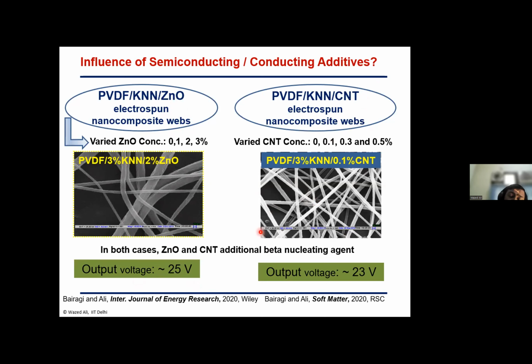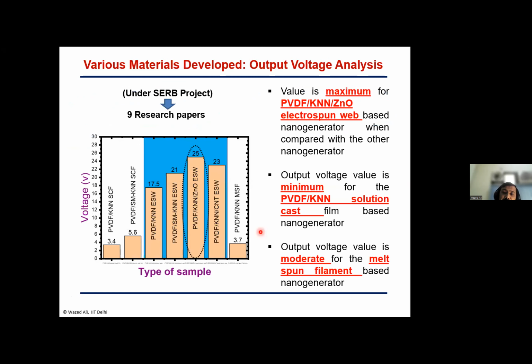So if you incorporate this kind of semiconducting filler or maybe conducting filler in the structure, we can expect higher output voltage, because it will facilitate the movement of the charge within the structure towards the electrode, top and bottom electrode of the material. So if you compare these different processes, for example, film, then surface modified filler along with PVDF, then electrospun, then surface modified electrospun, then even the combination of PVDF, KNN, zinc oxide, PVDF, KNN, and CNT. So there is some variation, right?